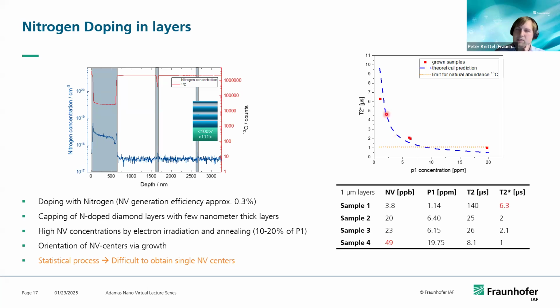But what you see in this plot here is also that with these layers that we produce, we reach these theoretical limits. And in addition, with this isotopical purification, we reach effective spin dephasing times of up to 6.3 microseconds at the moment. If you go for non-isotopically enriched diamonds, the maximum you can achieve is around 1 microsecond.